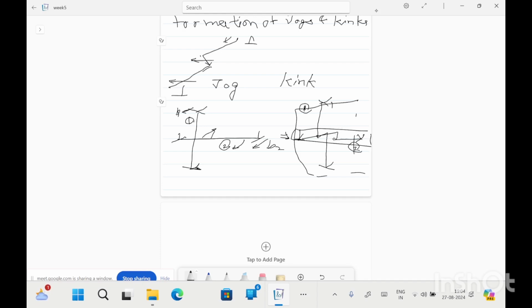So the Burgers vector will not change. If the Burgers vector is in this direction, it will be this and this, and the line vector also comes to this. So this will form a kink of screw nature, because the Burgers vector and line vector are in the same direction, with a 0° angle. Similarly for this also, this is the Burgers vector and this is the line vector. So this will also form a kink.